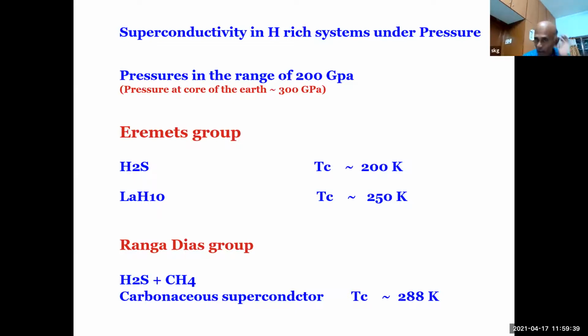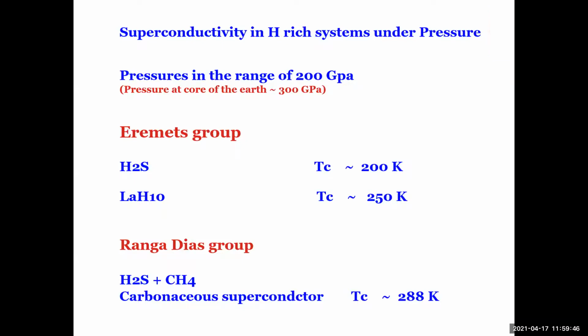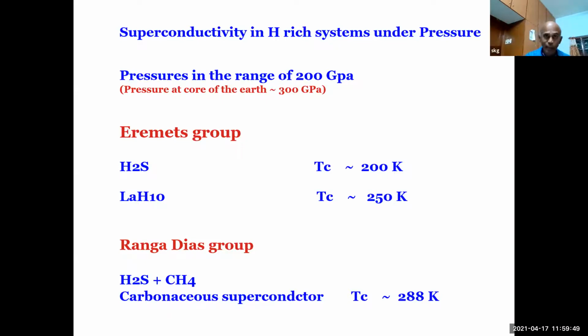Yeah. So I told you about two systems. It's amazing, because I always tell that supervisors tell that under pressure, every student works. So it seems that under pressure, even room temperature superconductivity is possible. It all started with Eremets, who found silane, SiH4, under pressure became a superconductor, 17 Kelvin. Then he pressurized H2S and it decomposed, and then it exhibited Tc of 200 Kelvin at huge pressure, 200 gigapascal.